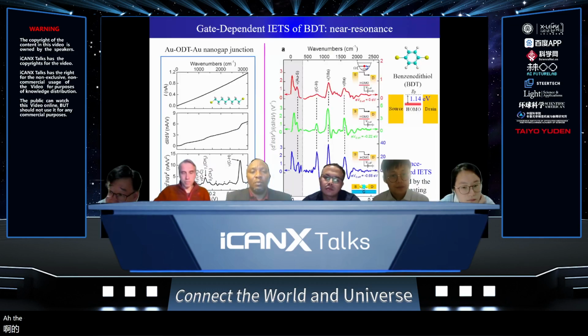The orientation, we cannot control, but the molecule automatically forms some tilting configuration or even a lying-down configuration with defects. But when you fabricate a molecular junction with top and bottom electrodes, we have an indirect method, the so-called electron molecular vibration coupling. It's similar to electron-phonon coupling. This coupling signal has different peaks, one high, one lower, depending on whether the electron passes in the direction of direct coupling to the molecular vibration.